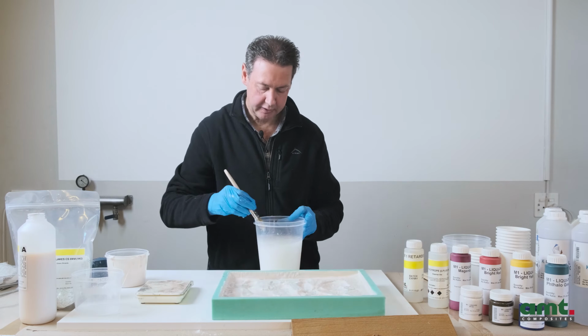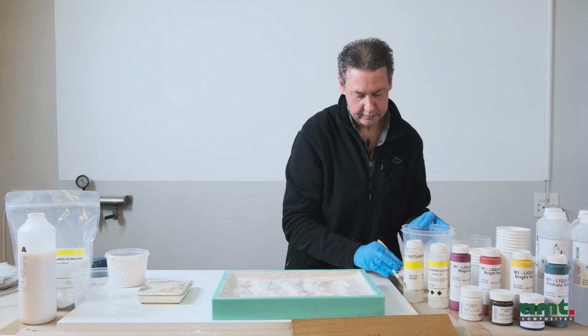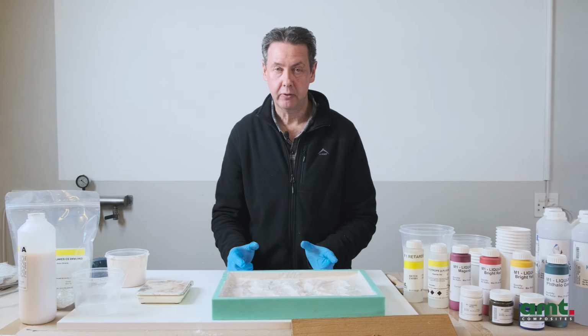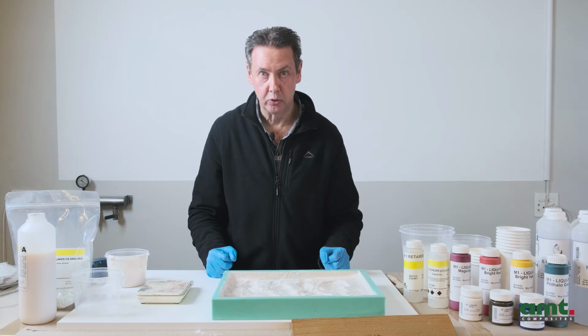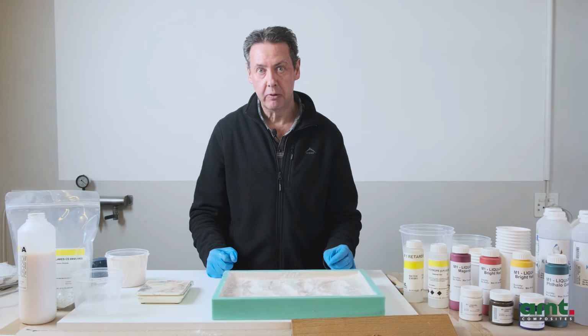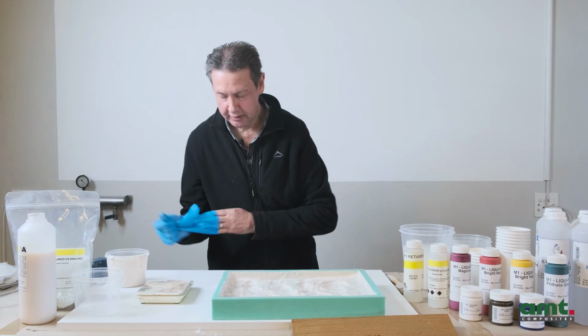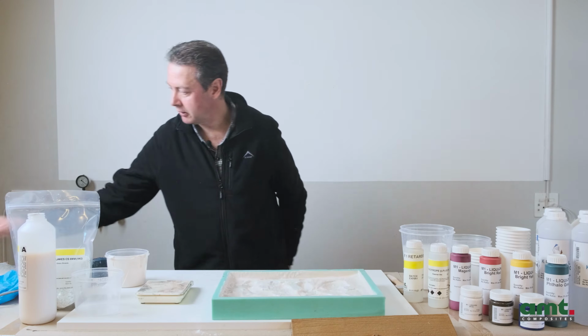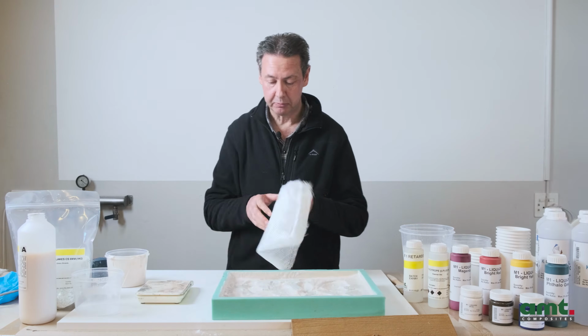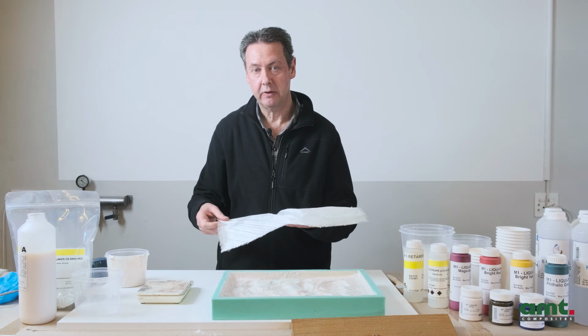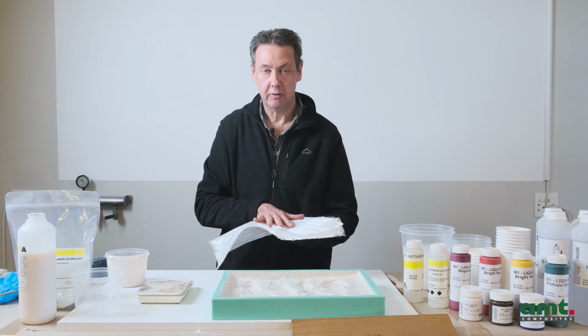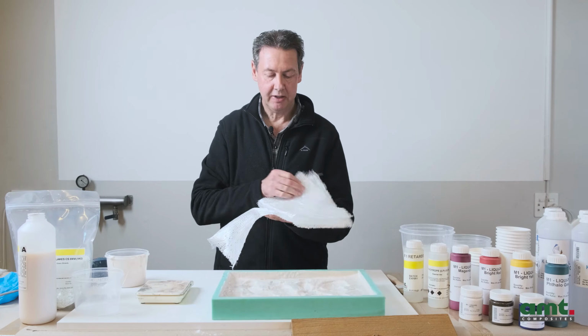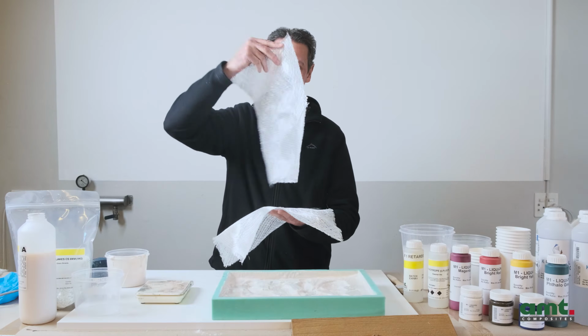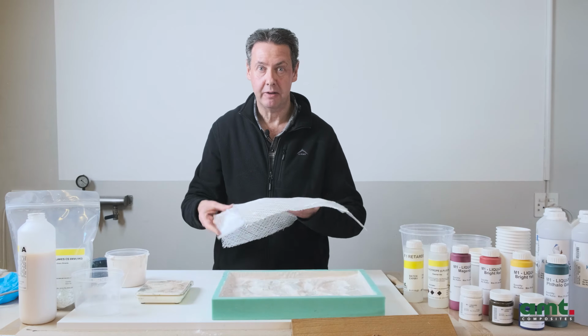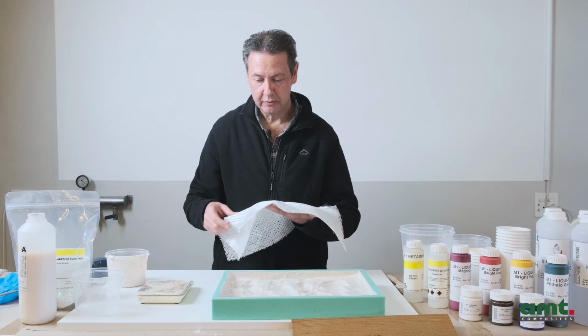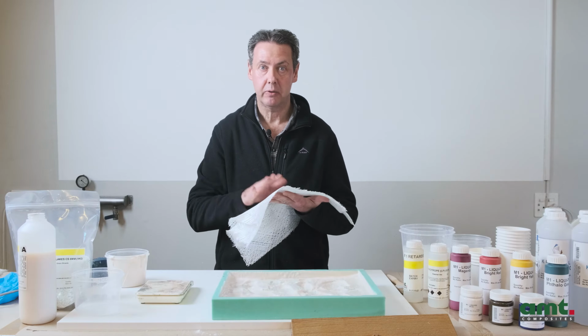So our brush is rinsed and ready for the next one. So what we need to do now is wait for this first layer that we put in here, this face coat or gel coat layer, to become touch dry. The reason why we wait for this gel coat to become touch dry is because when we put the fabric in for the reinforcement, this is where we're going to get our strength from, this glass reinforcement, we're going to have to laminate this down onto the surface. And if this is still wet, we're going to push this fabric through to the face coat of that piece. So we don't really want this 0/90 plus 45 minus 45 glass pattern coming through to the front of that laminate. So that's why we wait for this to harden up quite nicely. That's going to take probably about 20 to 30 minutes, and then we can start with the glass reinforcement.